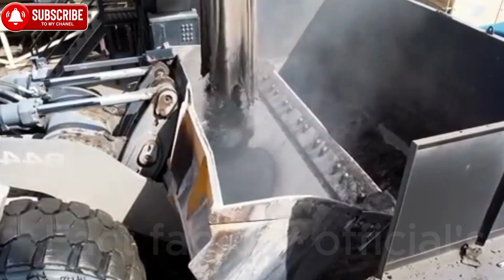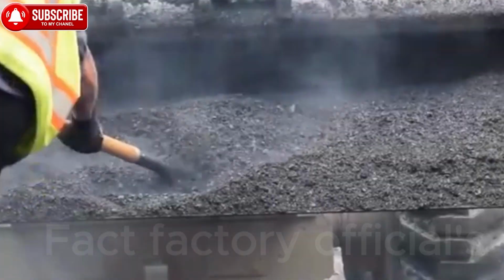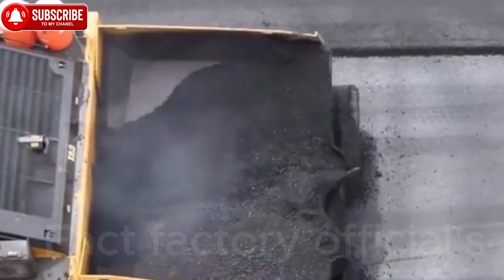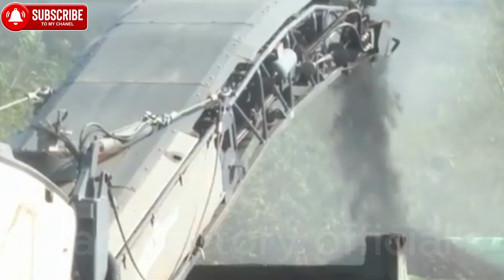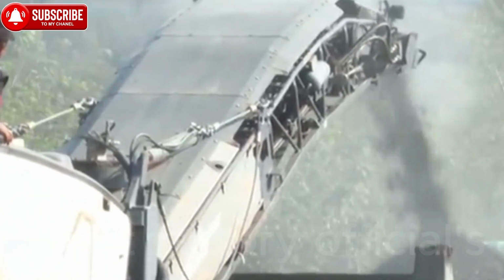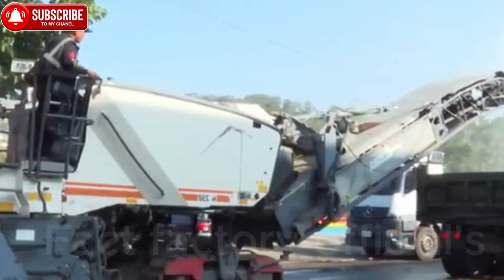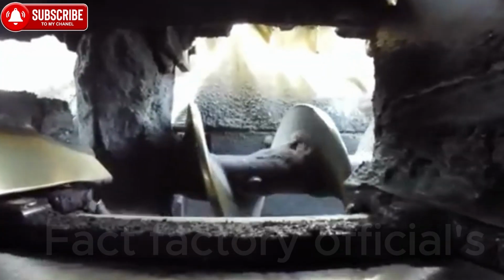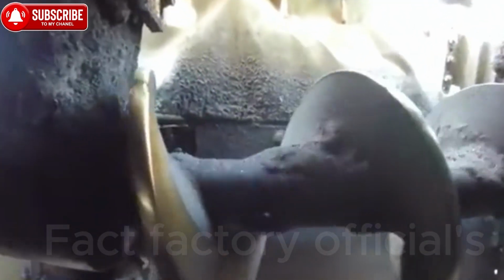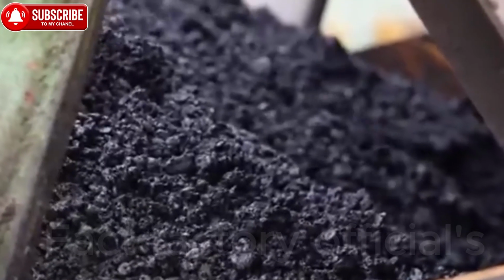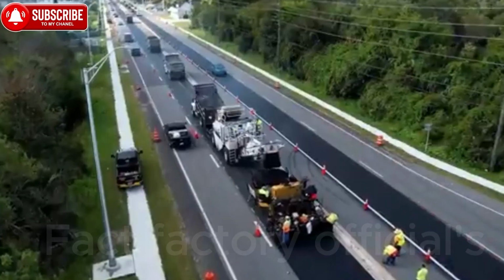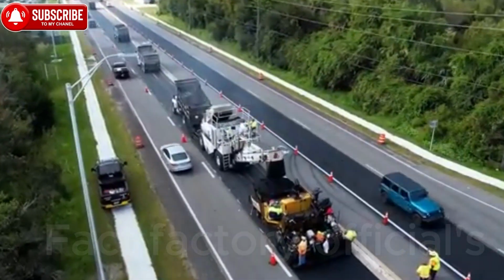First comes the smooth steel drum roller, giving the mat its initial compaction. Next, the rubber tire roller, weighing tens of tons, presses the aggregate tightly together, sealing the voids. Finally, the vibrating steel roller finishes the surface, increasing density while leaving it smooth and even throughout. The entire process is closely monitored by the temperature of the mix, because once it cools below 200 degrees Fahrenheit, about 95 degrees Celsius, the asphalt hardens and loses its ability to bond.